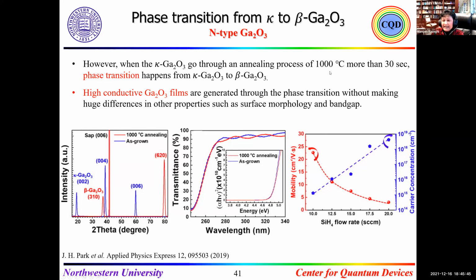We did annealing at 1000 degrees for 30 seconds, and I did it two ways - annealing in situ, and annealing ex situ with rapid thermal annealing, the same way we do for gallium nitride and aluminum nitride for the p-type.